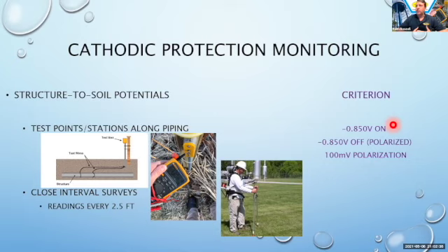So to eliminate those voltage errors, all the current sources that provide cathodic protection to that structure are synchronously turned on and off on a set cycle, maybe like a 3 second on, 1 second off type cycle, continuously throughout, so that they can still obtain an on potential. But as soon as those current sources turn off, we can obtain what I'll call an instant off, or really that's the polarized potential of that pipe.